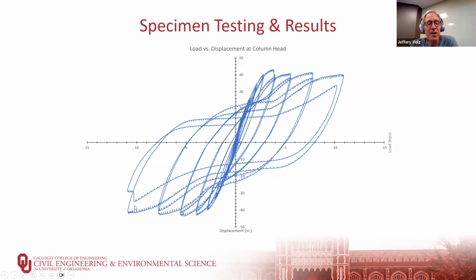So very good stress strain response, very good load deflection response, nice, fairly consistent in the beginning, non-deteriorating response, non-deteriorating hysteresis loop, a lot of area in here to absorb a lot of energy. And that's good for these multi-hazards, which are dynamic in nature. And if you can absorb the energy, you lower the effective loads that are acting on the element.